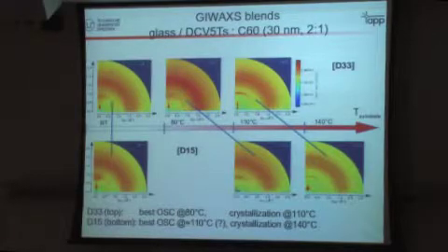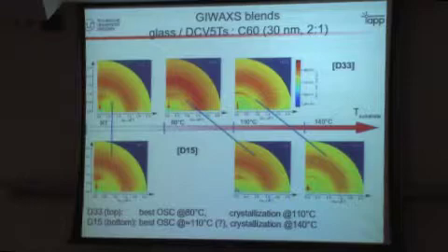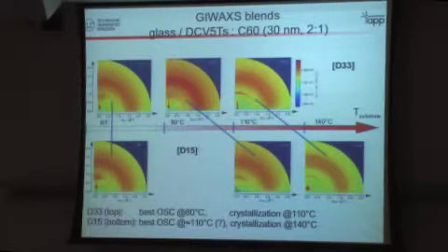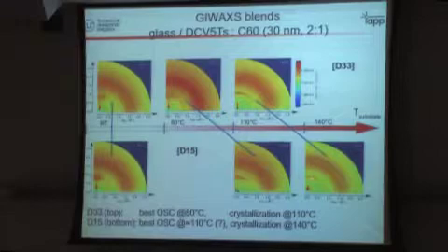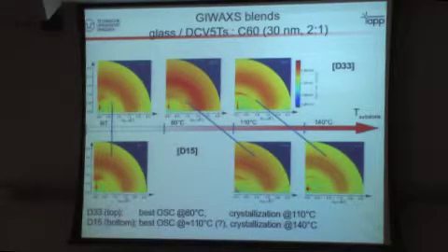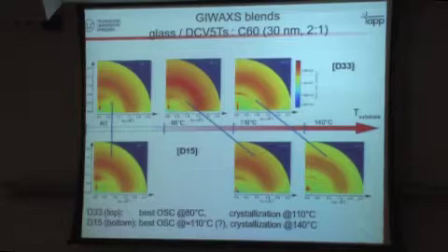However, when he then did measurements of the bulk heterojunction, DCV5 and C60, he noticed that we had overlooked a subtle effect. When you go for compound 3, for instance, from room temperature to 110 degrees, you see that there's a much higher order at 110 degrees. But absolutely the same effect is happening for compound 1, but at higher temperature. So the problem was that we had overlooked that due to this small difference in the methyl side groups, the materials obviously needed different temperatures for optimization.